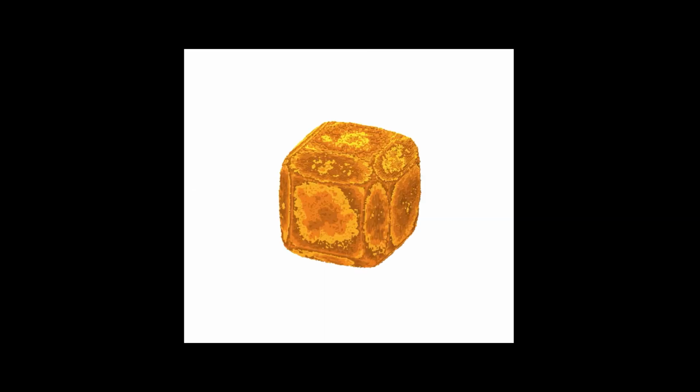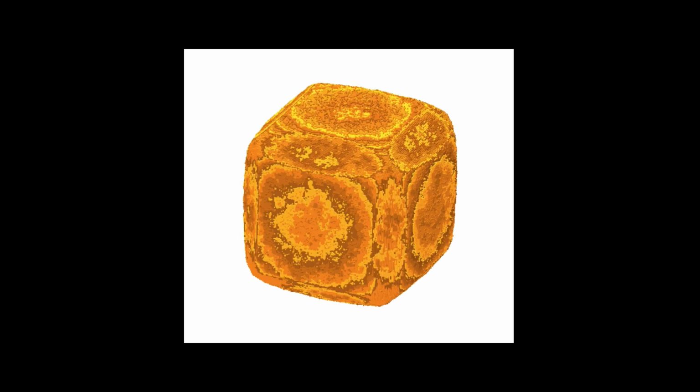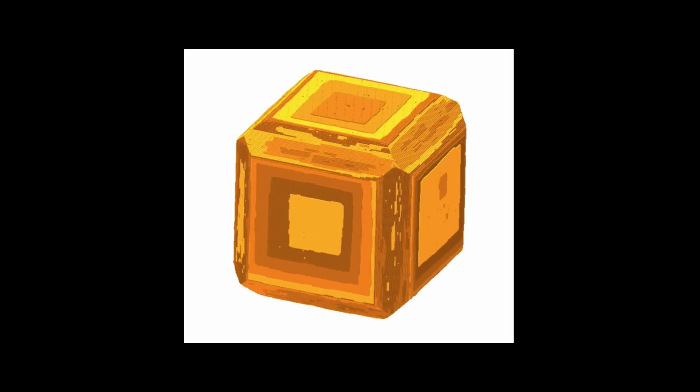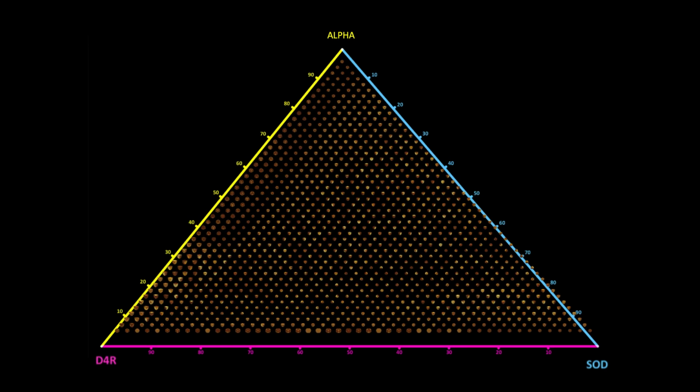So then if we grow the crystal in silico, first we start at high supersaturation, so we're getting a lot of surface nucleation. Then we're lowering down towards equilibrium, we're getting Ostwald ripening, and then we get the final habit of the crystal and the surface topography of the crystal. We can do that simulation on a laptop or a supercomputer. We can just do that to a certain size, even within a few minutes, and consequently we can do thousands of different simulations if we wish to.